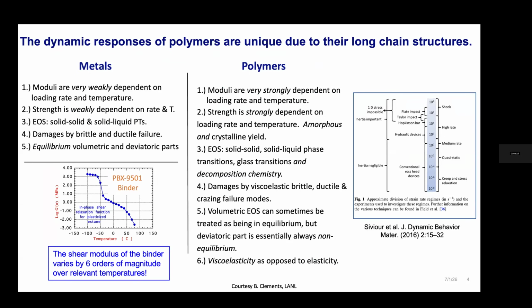So this first slide is actually borrowed from a colleague of mine from several years ago when we had a program on this, just highlighting some of the differences of the dynamic responses of polymers compared to metals. If you go over here to the polymer side, what you'll see is that the moduli and the strength are strongly dependent on the loading rate as well as the temperature compared to metals. Much stronger rate dependence with viscoelasticity. Also, polymers are often multi-phase, so they typically could have amorphous and crystalline domains as well as fillers within them. And so we have to capture those different domains because those domains dominate the properties.